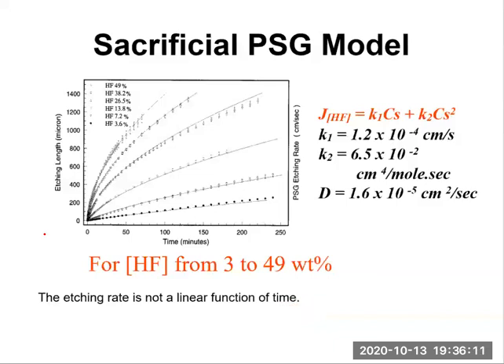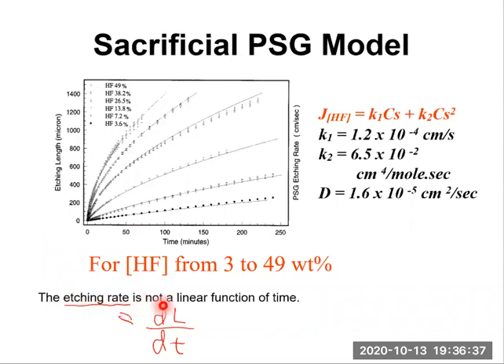Note that the etching rate is equal to the slope of these curves. Namely, it's equal to dL over dt. L is the etching length, t is the time. So that's simply the slope of the curve. We can observe that this etching rate is not a linear function of time. Or we can state that the etching rate decreases when the etching length L increases. So the etching rate decreases over the etching length or over the etching time.